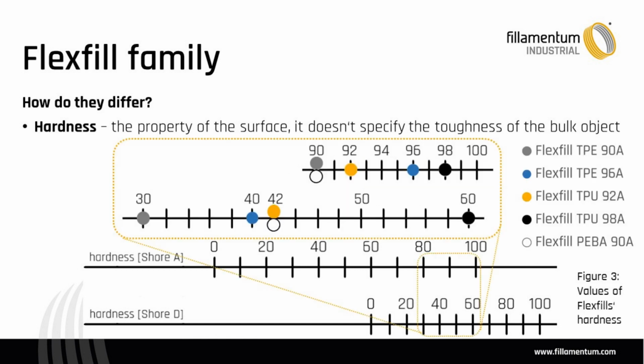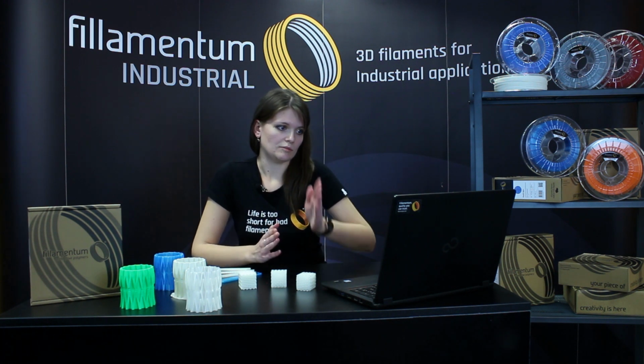And it can clearly be seen that, for example, Flexfill TPE is so specific by its mechanical property that 90 Shore A means 30 Shore D, because it has SEBS in its structure. So when we apply approximately 5 times more load and a different geometry, it just doesn't resist so much; it should be about 45, but it's 30.